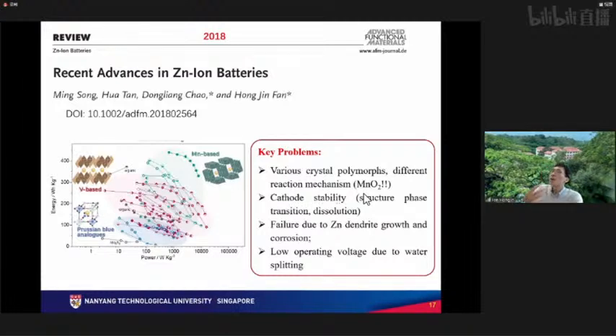The cathode material can have phase transitions during the first discharge. And the phase transition is sometimes irreversible, and a layered structure may become a non-layered one, if the structure is not engineered with a pillar effect. They may also have dissolution problems. So most manganese and vanadium cathodes are soluble in the aqueous solutions. Batteries also fail due to zinc dendrite growth, as well as corrosion. Corrosion is a very evident phenomenon for zinc anodes, because of the water splitting reaction and because of local pH changes, right? Also, because of the aqueous nature, they have a low operating voltage. So these are key problems faced by aqueous zinc-ion batteries.